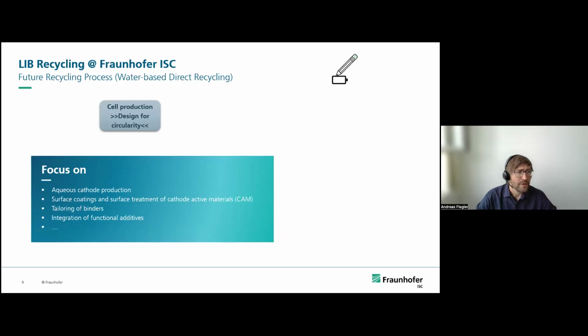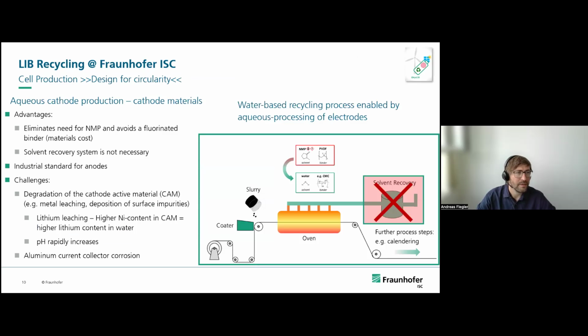So for the cell production, we're focusing on the aqueous processing for cathodes, and here we need a surface coating and the tailoring of binders and also the integration of functional additives. First, the aqueous cell production. Here we see it as a design for circularity. We have a lot of advantages. So we eliminate the NMP and also the fluorinated PVDF binder, and we don't need a solvent recovery system in the production anymore.